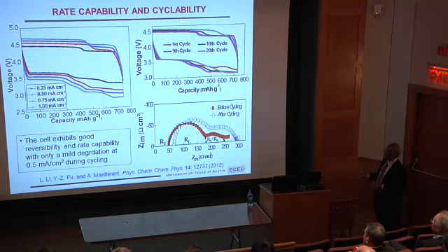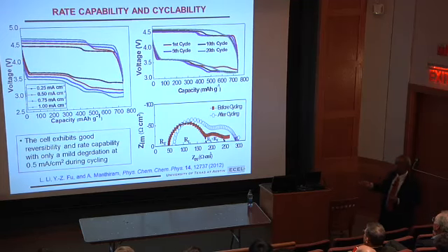And this is what I was talking about. The catalyst, this is a discharge voltage, that's a charge voltage, there is a gap, that is not good. We do not have the magic catalyst which will have lower overpotential during oxygen reduction and lower overpotential during oxygen evolution. So somebody has to develop a good catalyst.